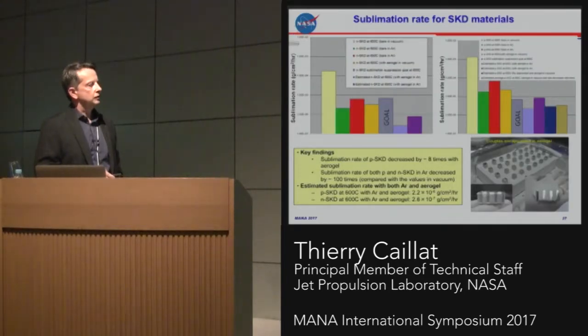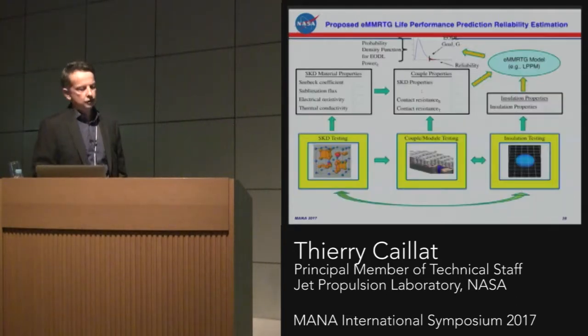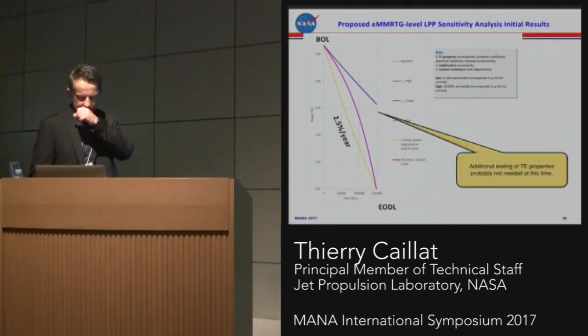Sublimation rate, again, we're using our aerogel to control the sublimation, and we have achieved sublimation rates which are consistent with what we need to achieve our degradation rate, our performance goal for the 17 years of operation. So this is the reliability approach, where we look at the different degradation mechanisms, define density functions for all those parameters, and combine this into a life performance prediction using a life performance prediction model.